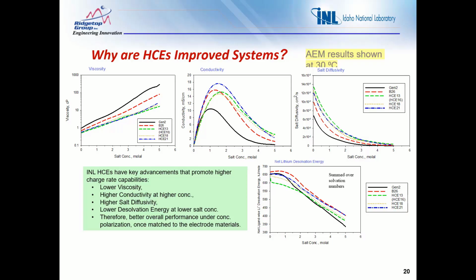Given that case, we have to balance transport behavior with desolvation behavior. We found systems that are not only low viscosity, but possess higher conductivity at higher concentrations, so the window of conductivity is wider. Also, they have higher salt diffusivity than the baseline carbonate system, and they also have lower desolvation energy at low salt concentration. When you run a cell under fast charge, you have a depletion of electrolyte on the anode side and an enrichment of electrolyte on the cathode side.